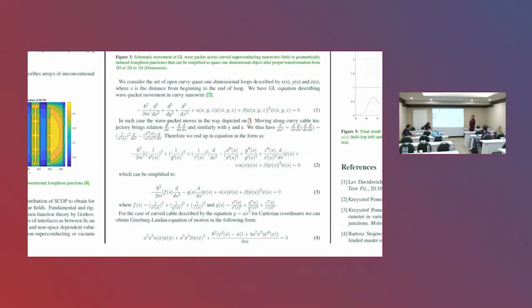So this term can be seen as part of dissipative term. However, we still can also think backwards using analogy to vector potential. So we can have an imaginary and real component of artificial vector potential that is introduced by curvature of cable. So anyway, having the curvature y equal a x squared, we deal with such type of effective equation where alpha and beta field is dependent on x.